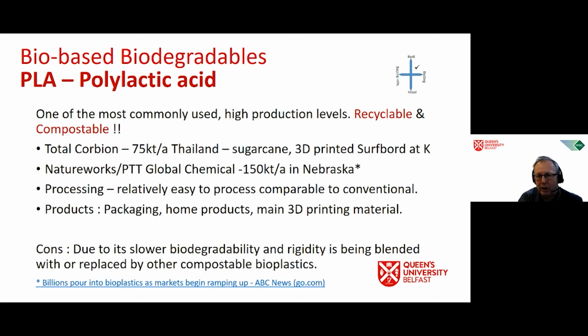Just going back to PLA, as I said, it's historically one of the most commonly used bioplastics, and there are many suppliers. However, NatureWorks and Total Corbion are two of the larger producers, with capacities of 150 kilotons per year and 75 kilotons per year, respectively. PLA is relatively easy to process in line with conventional equipment and conventional materials, so it's not a big step for producers. However, PLA, polylactic acid, is a polyester, and like PET, it requires drying to very low moisture levels.